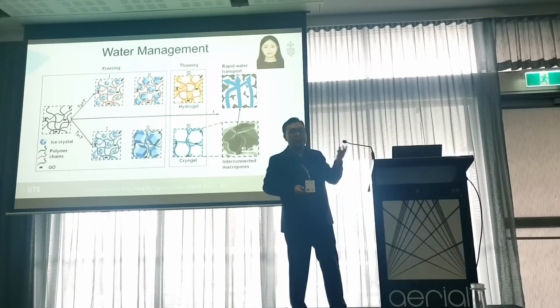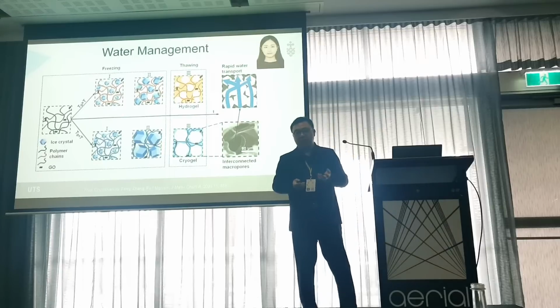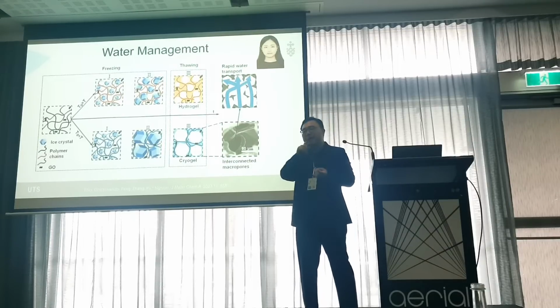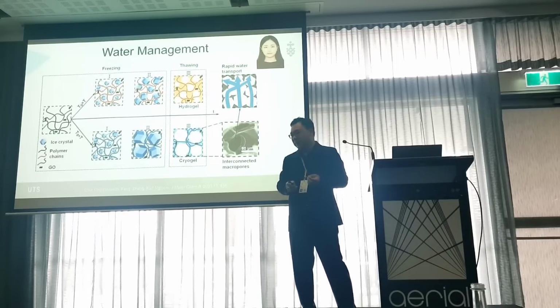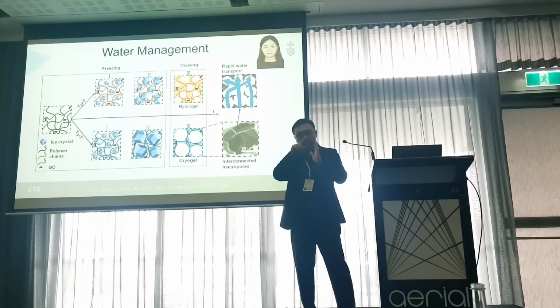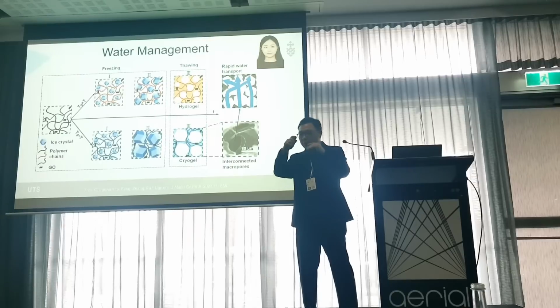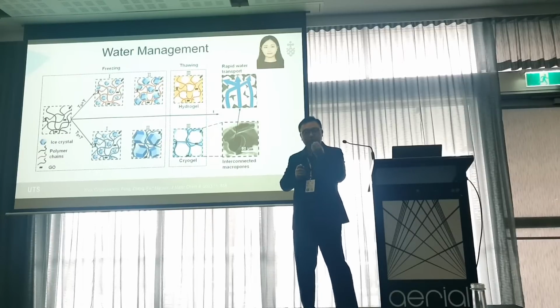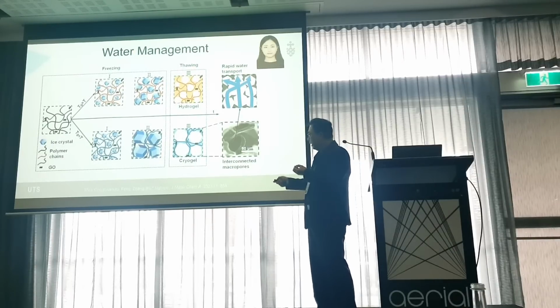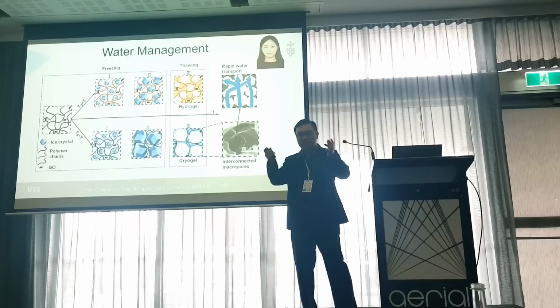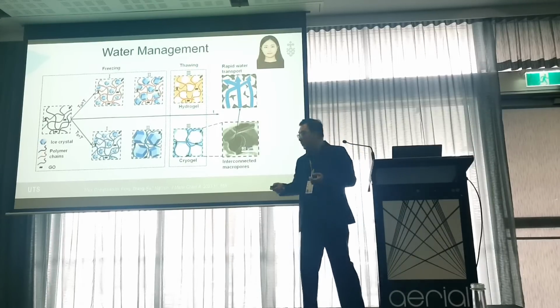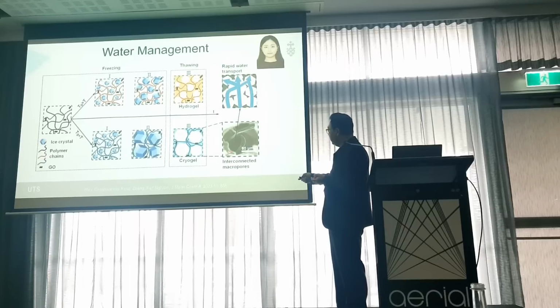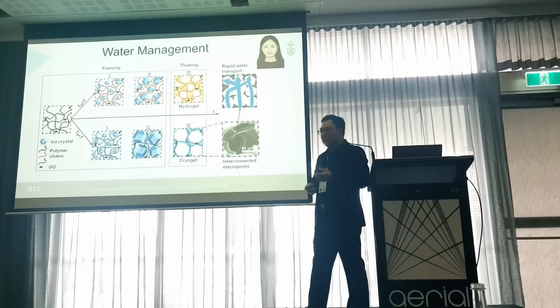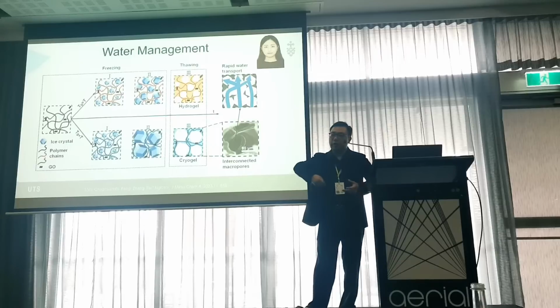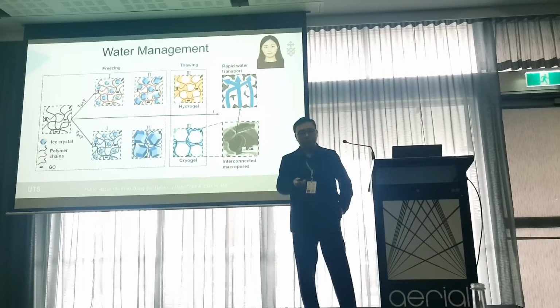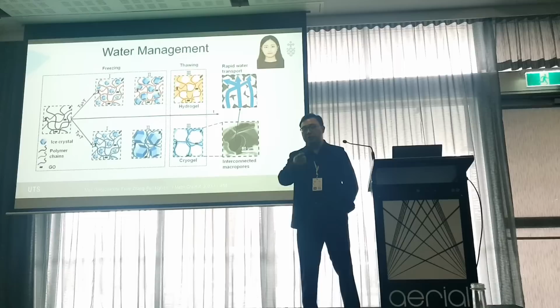However, in the case of PEG hydrogels, the Tg of them is very low, below -40 degrees Celsius. So therefore, during the frozen process at -18 degrees Celsius, the polymer chain still shows high mobility. So the water crystal in this hydrogel can grow larger and larger, not limited by the polymer chain. So finally, we will obtain very large pore size, yeah? And they are interconnected. And this structure, as I said, is expected to show high water transport, rapid water transport, and eventually facilitate water evaporation.